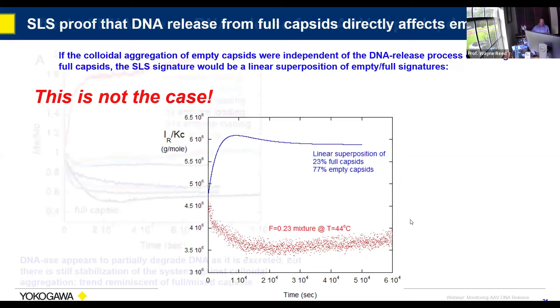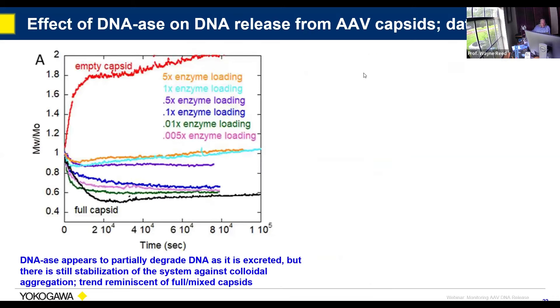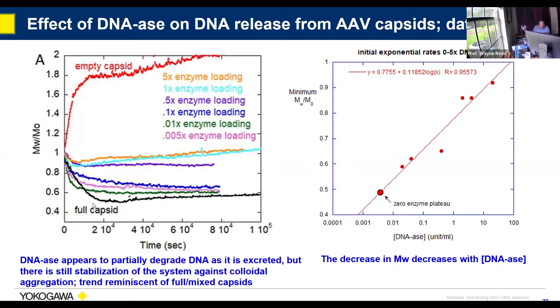We also looked at the effect of DNase on the release. At one extreme, 60% full capsids release DNA; at the other extreme, empty capsids show colloidal aggregation. By increasing the dose of DNase, we bring the behavior more toward the empty-capsid colloidal aggregation type. This suggests that as DNase chews up the released DNA, it ruins the DNA's ability to prevent aggregation. The minimum in the scattering gets shallower and shallower with more enzyme, confirming that somehow the DNA is inhibiting aggregation.